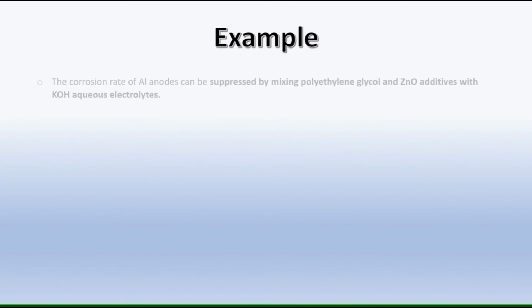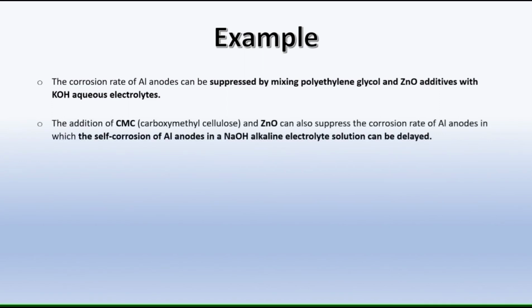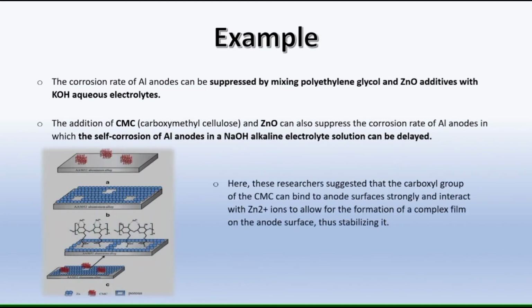For example, the corrosion rate of aluminum anodes can be suppressed by mixing polyethylene glycol and ZnO additives with KOH aqueous electrolytes. The addition of CMC and ZnO can also suppress the corrosion rate of the aluminum anode, in which the self-corrosion of aluminum anodes in NaOH alkaline electrolyte solution can be delayed. Here, these researchers suggested that the carboxyl group of CMC can bind to anode surfaces strongly and interact with Zn2+ ions to allow for the formation of a complex film on the anode surface, thus stabilizing it. Here, the figure is showing the process of suppressing the self-corrosion of the aluminum anodes.